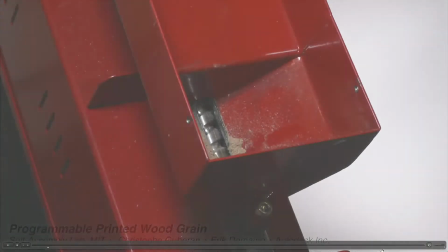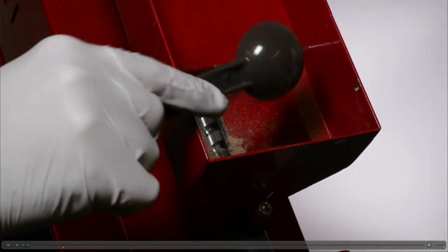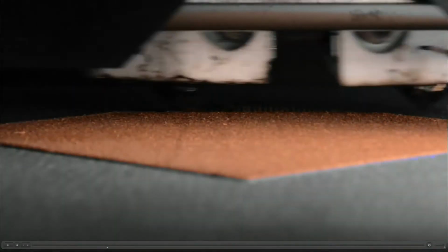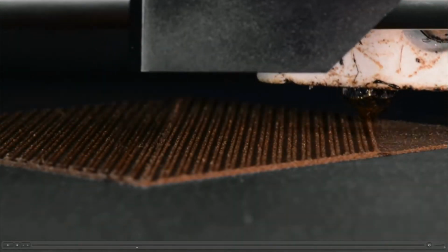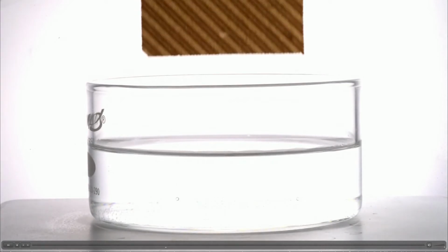By printing wood, you can take the behavior of the wood, the cellulose is going to swell with moisture, and we can then create our own grain. We can make any grain that we want. So the way to do that is that we combine sawdust and plastic to make a filament that we can extrude with. You can now actually buy a wood filament to print with. We then print with it an FDM printing process where we make two-dimensional and three-dimensional grains. So we create our own custom grain, we print them out, and then you get them wet.